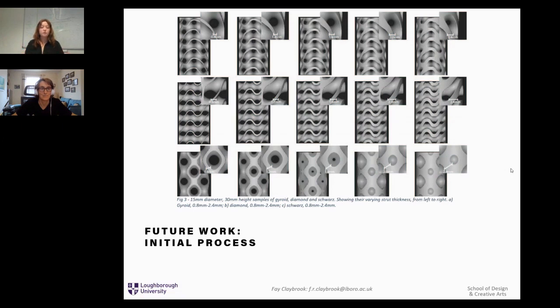So the compression samples for this study were taken the exact same as the Schwarz P structures, but instead of 5 samples for each, 7 samples were made. And the initial plan was to do this for both TPUs, but due to 60A being so malleable, there was a lot of pressure buildup in the nozzle, so that had to go to a 0.8 millimeter nozzle rather than the standardized 0.4, and could only replicate the larger strut thicknesses, so the 3 on the right, so the less porosity, so the 1.6 millimeter to 2.4 millimeter strut thicknesses.